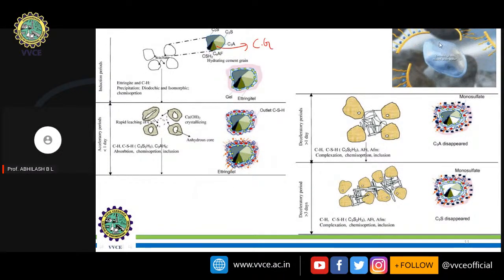Fine. You can observe some of the chemicals which accumulate in a cement particle. Let us assume that this is a cement grain, where the C3S, C2S, and C3A are proportionately differentiated. If you observe an electron microscope image of these cement granules, you can see the different particles accumulating on the cement grain. This leads to the different heat of hydration, and oozing out of water from the concrete, which is what you call bleeding of concrete. All these are majorly due to the Bogue compounds. If you understand the Bogue compounds, then concrete technology will be somewhat easy.